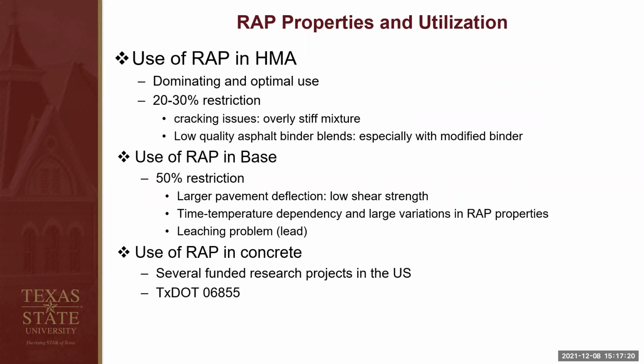So on this slide, I'm summarizing the common practice of using RAP in our construction materials. I think we all know the most dominating and probably the optimum use of RAP is to use RAP in HMA, hot mix asphalt. However, there are some issues related to these applications. The primary issue is related to the aging of asphalt in the RAP. Because of the aged asphalt, the new mixture, if we put too much RAP, it will become very stiff, and we will have some cracking issues in our asphalt pavements.